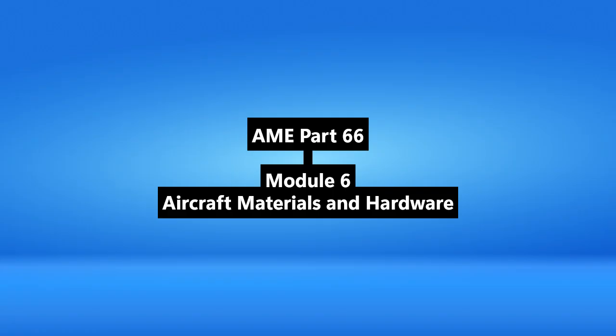Bonding and grounding. Why so important? Vital for safety, proper operation. Bonding creates low-resistance connections between conductive parts, keeps everything at same potential. Why? Dissipates static charge buildup from flight friction, prevents sparks, fuel vapor risk, damage to electronics. Static bond resistance, 1 ohm typically. Ground provides return path for current, references equipment to common ground potential. Bond ground resistance tested, ideally 0.003 ohm for good current flow.